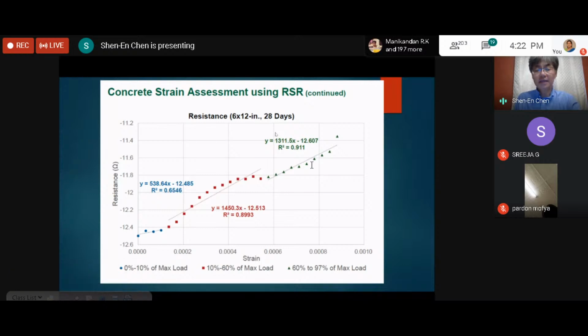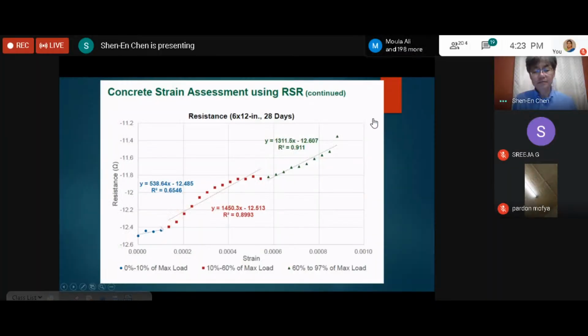And previously that was the 7-day concrete. And then for the 28 days concrete, we actually were able to distinguish 3 different phases of the transition. And then we make a correlation. So you can imagine during the small strain loading, because of the loading setting, you are expecting to have a larger deviation of your measurements. But then as you load to a higher strain level, you will get a more consistent measurement. So this gives us a lot of confidence in the self-sensing capability of this concrete material.